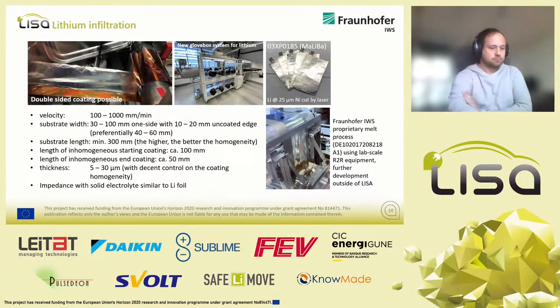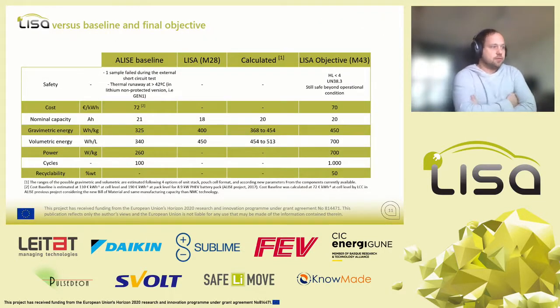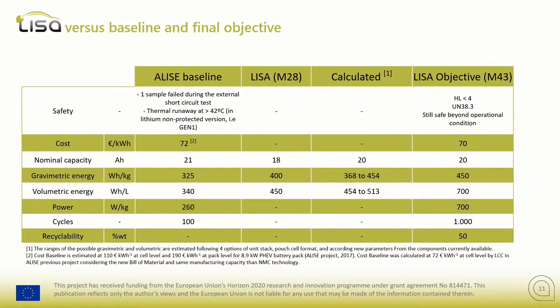Another process is being developed at pilot level by Fraunhofer, also developed in other projects like Maliba. Today they are able to do it at pilot level. The process consists of melting lithium and printing it on top of the current collector as liquid metal. Here you can also use a lower quantity of lithium and optimize your cell. Our current statement is about where we are, where we want to go, and what we think is still possible regarding energy density to fit with the final objective. Our top priority since one year ago is to work on safety and cyclability, though we do not yet have results to show on this.